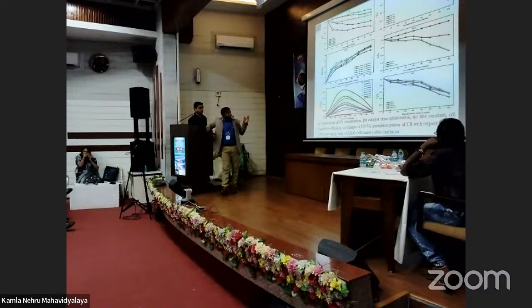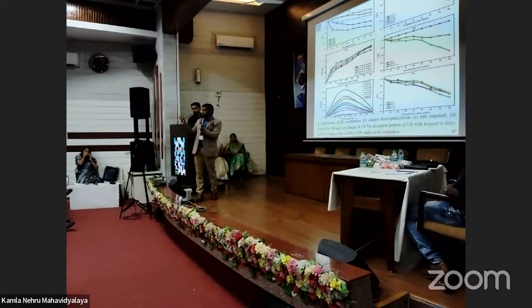Next. Similarly, we also tested the material for dye degradation. We took the CR dye, and this was published in ACS Omega. This indicates the dye degradation. In earlier talks it was said that degradation means radical formation, and the color changes to pure white. That alone is not an indication of degradation. It should degrade the radicals, and the materials should be totally different. So here we were successful in finding the degradation of dye using these bio-inspired materials.